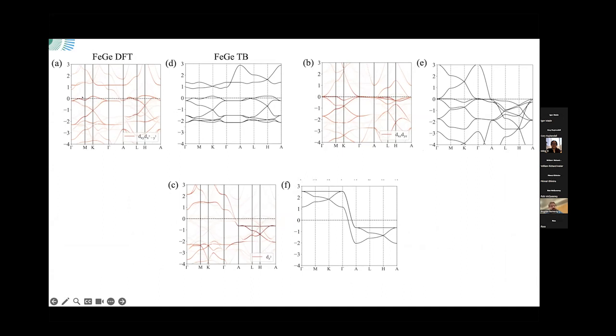Now you can see that there are flat bands at the Fermi level, but you can also see that in the DFT there are flat bands below the Fermi level at -2. And this Hamiltonian, this is our tight binding Hamiltonian. It's basically a deformed line graph. It's a deformed bipartite Hamiltonian. And you can see that it clearly gives you these flat bands.